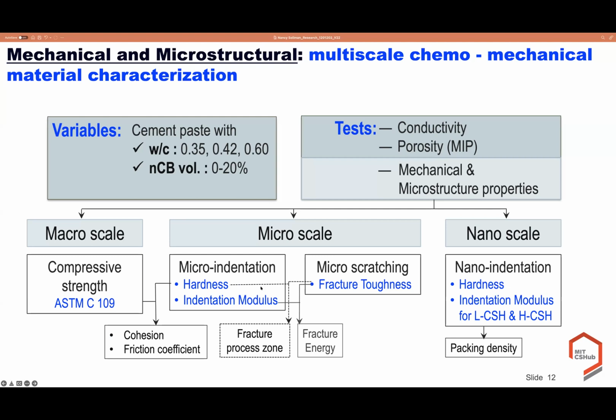From fracture toughness and hardness, we can estimate the fracture process zone, and from indentation modulus and the fracture toughness, we can estimate the fracture energy. And using the micromechanics model, we can estimate the packing density of CSH.